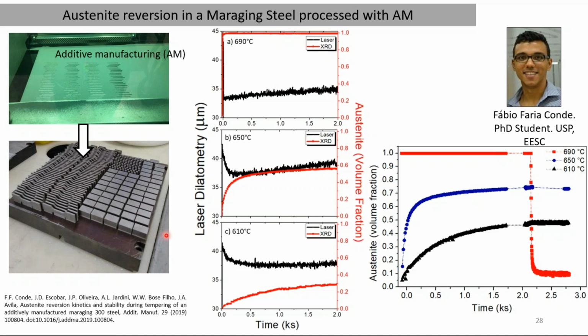We used them at the synchrotron, on the XTMS beamline, and we applied these 3 different isothermal treatments. We can see in this picture in the center the laser dilatometry obtained by the Gleeble, by the sensor we have there. And here on the right y-axis, you can get the austenite volume fraction. But let's jump to the right picture. You can see here the austenite volume fraction and the time during the test. Let's go for the highest temperature, 690.